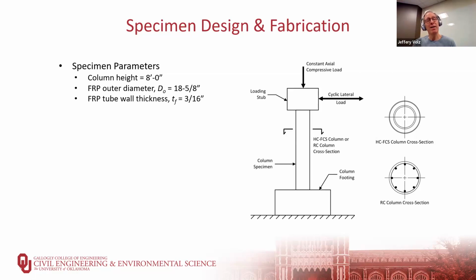That is the lower bound value. So that's the low seismicity equation for determining the thickness. The reason we chose that is because we wanted to ensure that we got the materials to fail. If we oversized them and they never failed, no matter how far we pushed it, we wouldn't know what the true capacity was. So we're at the lower end of that for this initial testing.